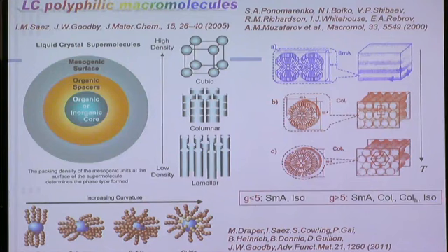So the objects are similar to compact colloids. Another factor, of course, is the temperature, because the conformational entropy will always try to make the thing spherical, and at high temperature, of course, it finally achieves this, and the system could form cubic phases. But if the temperature is lower, then competing mesogenic interactions, basically a competition between two tendencies, result in formation of either a lamellar smectic or, say, a rectangular columnar phase or hexagonal columnar phase, which was known from the study made in 2000.